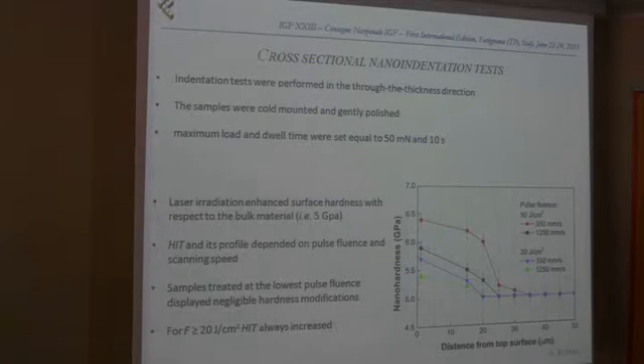In order to understand how deep the surface treatment was, so how effective the laser treatment itself was, we took a cross-section of our samples. We cold mounted it into resin, polished it, and performed nano-indentation tests in order to verify if the hardness was changing along the depth. And that's what's happening as well.